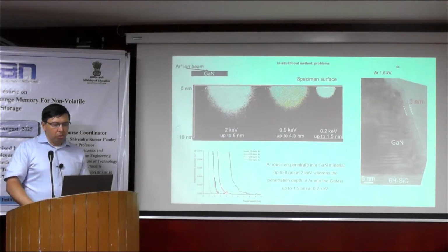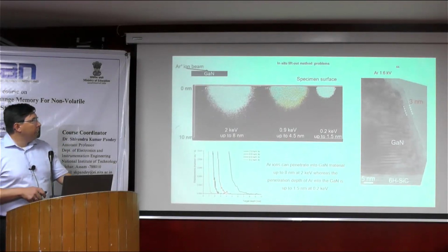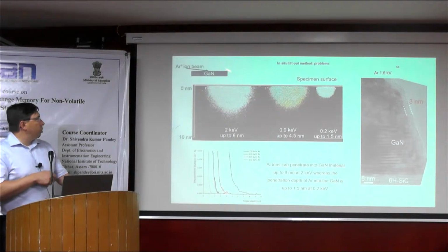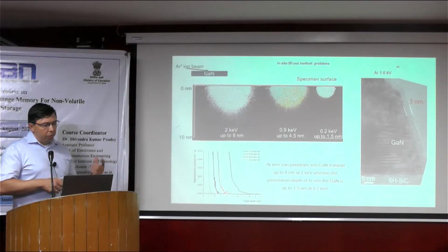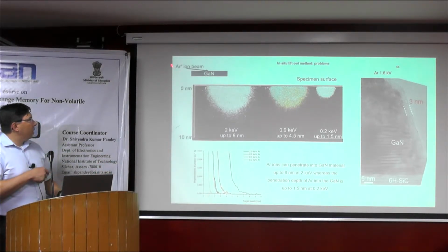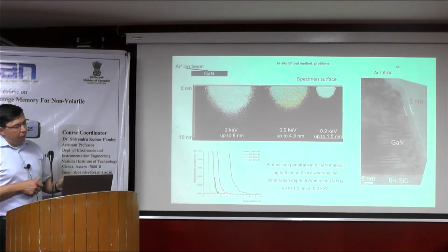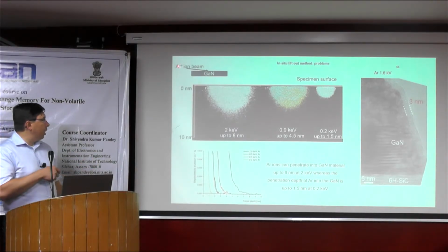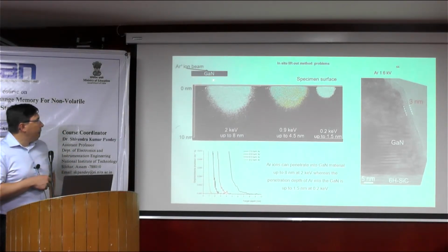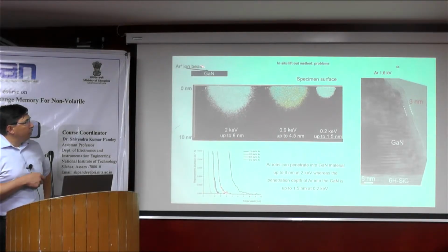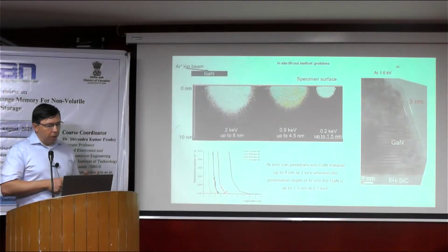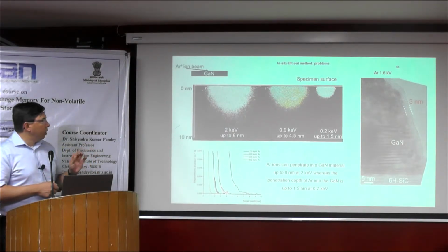You can also reduce the thickness of your specimen by using another argon ion beam system, the so-called nanomill. Here you also use a focused argon ion beam, but instead of gallium you use argon. Argon ions are a little bit smaller than gallium, and gallium is much larger than argon. By using this you can process your specimen thoroughly and get better surface quality and thickness.